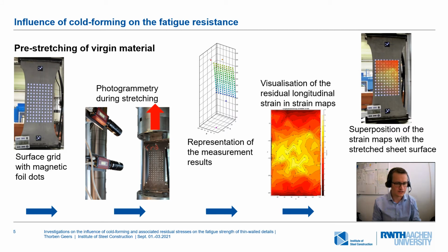To assess the influence of plastic deformation on fatigue strength, specimens from virgin sheets were compared with specimens from pre-stretched sheets. In order to determine the degree of plastic deformation, points applied to the sheet surface during stretching were documented using two high-resolution cameras. The resulting position of the points before and after stretching then allowed conclusion to be drawn about the stretching. Finally, the results could then be presented in complete strain maps, which you can see on the right side in yellow and red. The strain maps obtained could be used to quantify the strain values of the surface after superimposing them on the sheet surface.